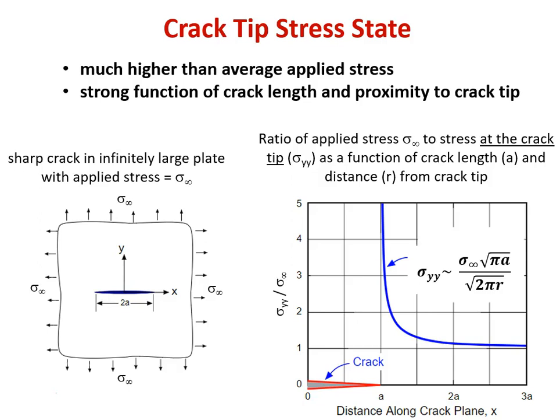So now we're going to focus on crack tip stress state, and this will be the beginning of deriving an expression for what we call K1C, or critical stress intensity factor. Critical for mode 1, plane strain, and this is the major data benchmark that you will look for in fracture toughness data for a specific material. So we're going to talk a little bit about where K1Cs come from, what they mean, how they relate specifically to applied design stresses, pre-existing flaw sizes, how they're tested, and how to use them. So starting at the beginning, crack tip stress state.